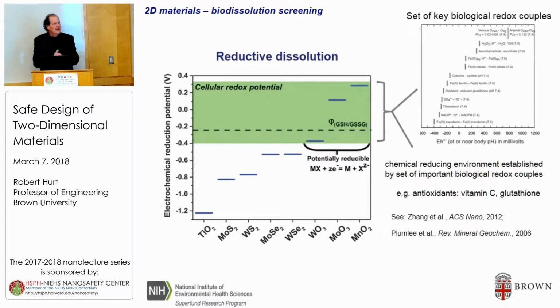But if you look at its chemistry, it's subject to reductive dissolution. And so this is the cellular redox potential concept that we borrowed from Andre. But if you imagine this expresses the electron energy in a biological system, and now we're plotting the electrochemical reduction potential of different materials, and we're comparing them to this redox potential band. And the materials that fall in or above that band are thermodynamically reducible under these standard conditions. And this redox band comes from a set of 12 different important biological redox couples. We don't have to go into the details. But it's driven by the antioxidants that are present, like ascorbic acid and glutathione and other molecules.